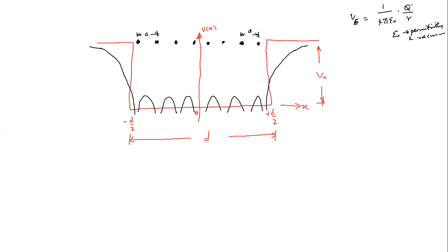this reduction of the Coulomb potential between the ions can actually cause the atomic orbitals to mix with those of their neighbors. And this will lead to the broadening in energy and the spatial extent of the electron charge distribution. And in metals, this can free the valence electrons from the atoms and allow them to roam freely in the whole solid. While in semiconductors, each electron may be freed from the valence band at the operating temperature by the solid and excited into the conduction band. This can drastically alter the characteristics of the solid.